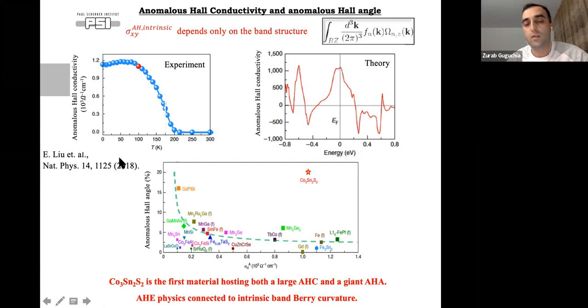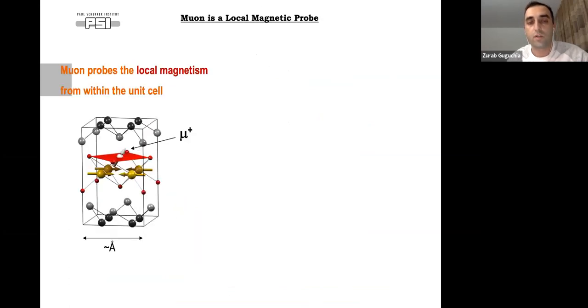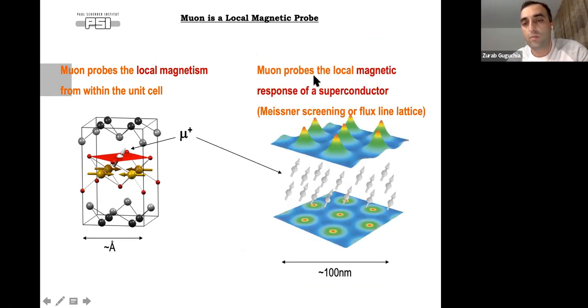So we decided to look at magnetism on a microscopic level and to see what the magnetic structure is, and if there is any connection between magnetic structure, magnetic properties, and the topological properties. For this, we used a local magnetic probe, which is called muon spin rotation, and the muon probes the local magnetism within the unit cell. It sits at the interstitial site, and it can probe its local magnetic environment. At the same time, you can also probe the local magnetic response of a superconductor, either Meissner screening or the flux-line lattice. So we can extract the local field distribution inside the superconductor in the vortex state. And I will give some more extended explanation for this.